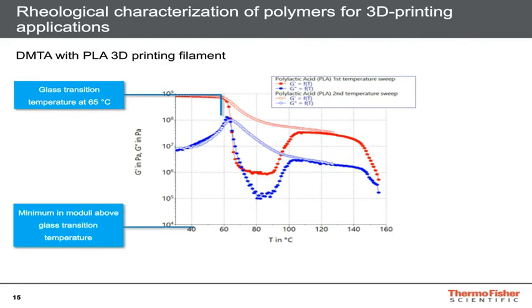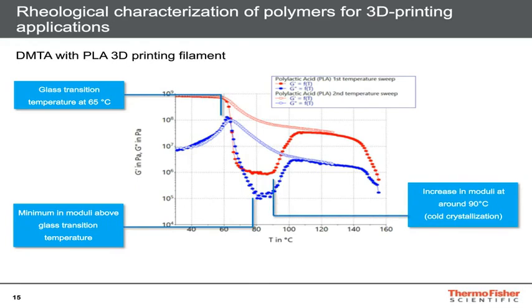And now the surprising part happens. At temperatures between 90 and 100 degrees centigrade, the values for both moduli started to increase again rapidly, before reaching another plateau. At temperatures above 140 degrees centigrade, the sample started to melt and those values were decreasing again. The increase in moduli between 90 and 100 degrees centigrade can be assigned to a phenomenon called cold crystallization that occurred above the glass transition and below the melting point.